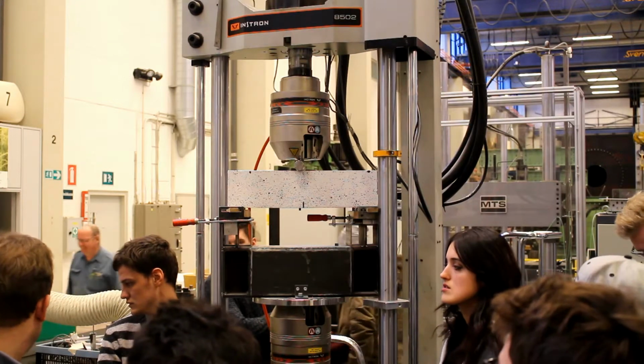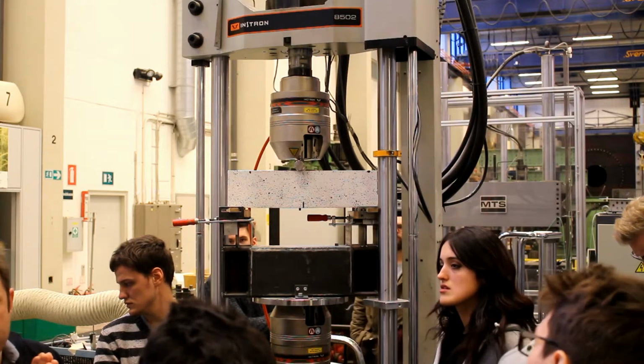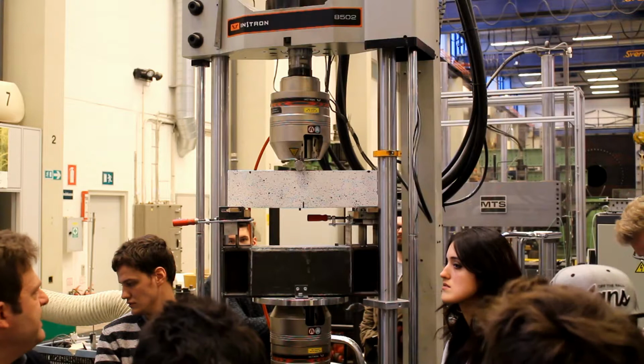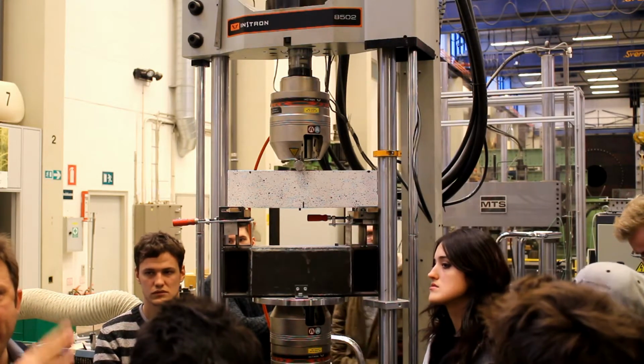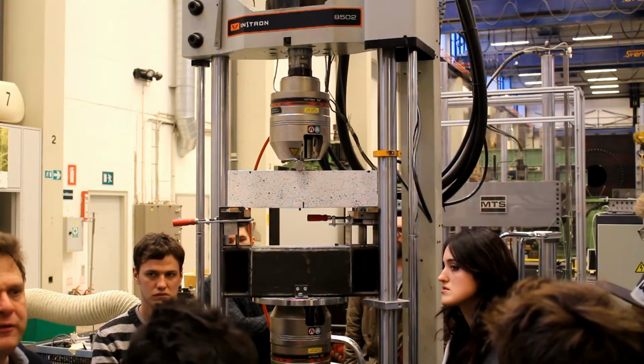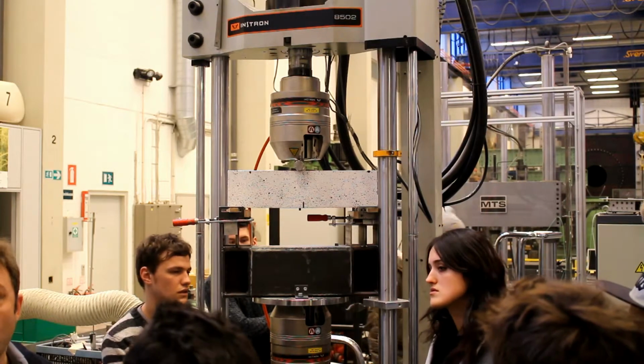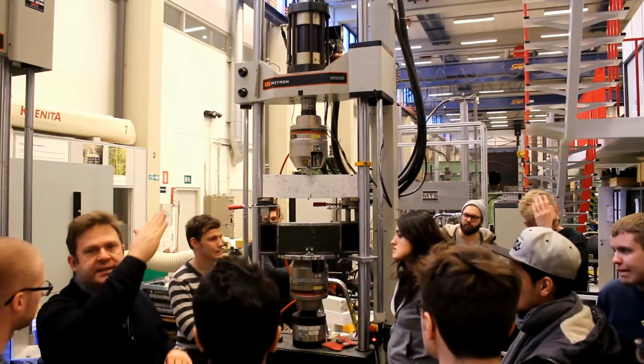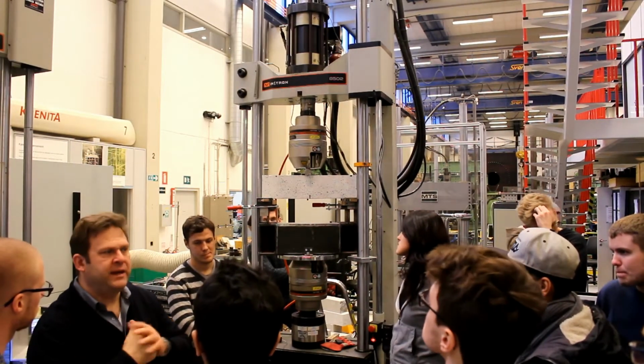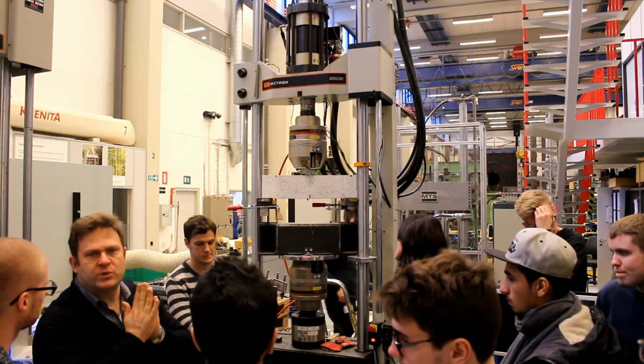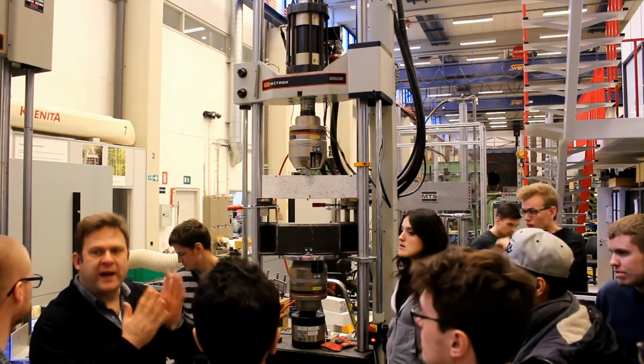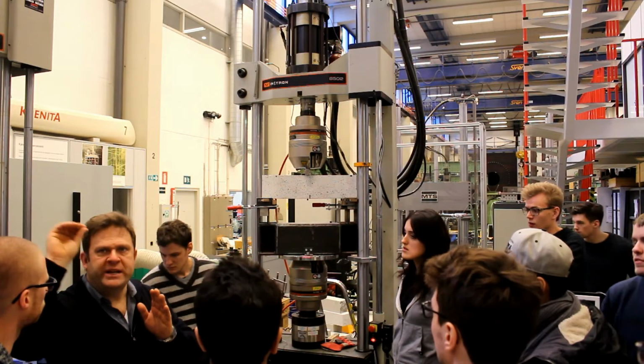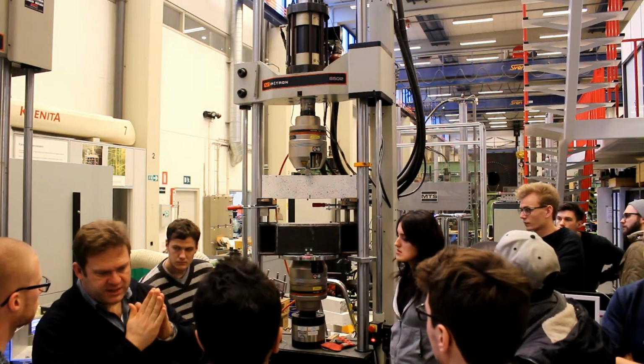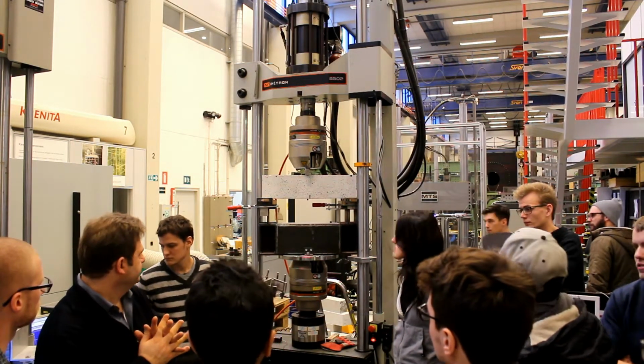and the load is dropping continuously. So this material here would have a softening after we have reached the cracking load. So it starts to lose strength as the crack continues to open. If you had more fibers, it would potentially gain strength as the crack is starting to open.